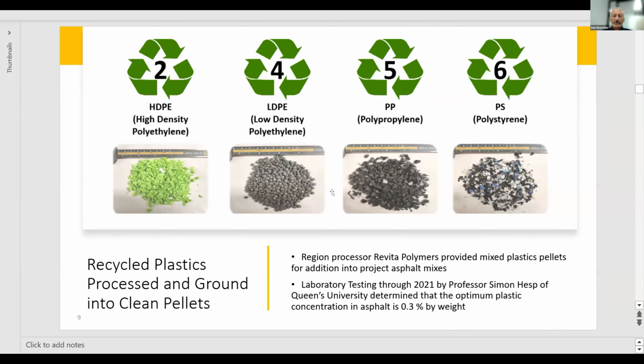We also partnered with Revita Polymers, who process our mixed plastic, and they provided mixed plastic pellets for addition into our asphalt mixes. It contained high density and low density polyethylene, polypropylene, and polystyrene. Extensive laboratory testing throughout 2021 by Professor Hesp determined that the optimum plastic concentration in asphalt is 0.3% by weight. Simon, I recall, I think you tested approximately 100 local asphalt samples with varied amounts of plastic in it to come to this conclusion.